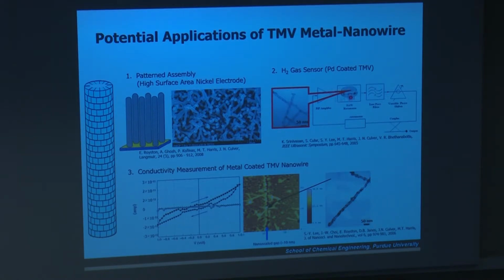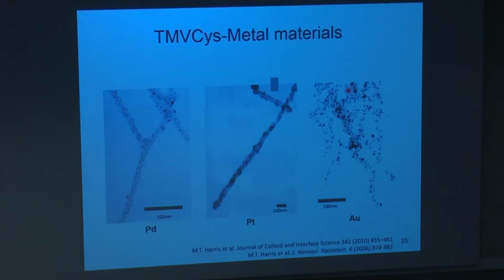because a lot of palladium sensors were a thin film of palladium on a substrate, and if the hydrogen absorbed, the palladium would swell, and if you remove the hydrogen from the environment, the palladium will desorb, and the palladium would shrink, and what happens is eventually the palladium would crack, and the sensor would fail. But in the case of these small nanoparticles, the palladium could absorb and swell and shrink, swell, shrink. You can circulate the hydrogen environment millions of times without failure of the device. So those are two applications for TMV, and there are probably millions of others that we hadn't thought about and that people are currently doing.